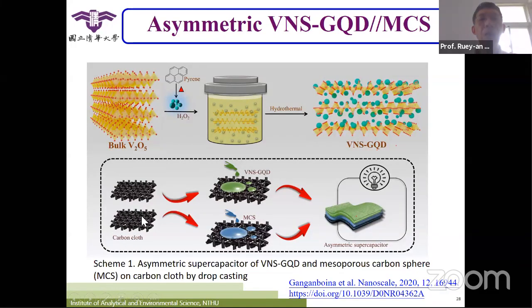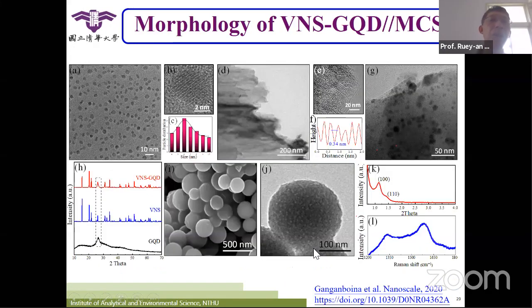And then we try to fabricate our negative electrode. We use carbon cloth and then put some three-dimensional material on it. We call this one the mesoporous carbon sphere. You will see their morphology here. So one electrode used is the VNS with graphene quantum dots, and the other electrode we use is the mesoporous carbon sphere. We merge them together, so we call this one an asymmetric supercapacitor. Okay, so their values will be here.